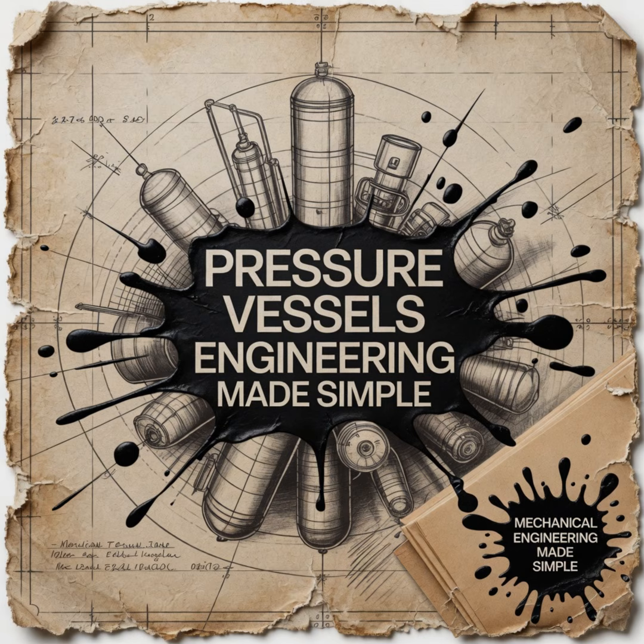Pitting doesn't attack the whole wall evenly. It is a highly localized, aggressive electrochemical drill that creates microscopic deep holes in the surface of an otherwise perfectly shiny, uncorroded piece of stainless steel. But wait, a microscopic hole in a piece of steel that's like 2 inches thick doesn't sound like a massive breach risk. Wouldn't it take decades for a microscopic pit to drill all the way through? The danger isn't the pit breaching the wall and causing a leak. The danger is what the shape of that pit does to the physics of the metal around it. A microscopic pit is effectively a tiny, incredibly sharp needle pointing directly into the thickness of the metal.